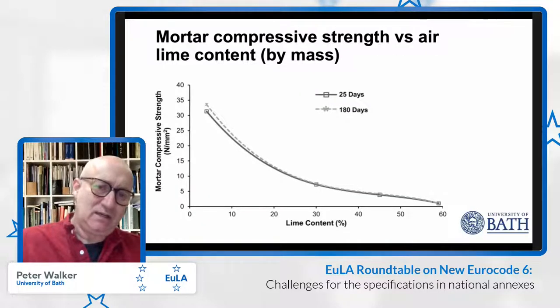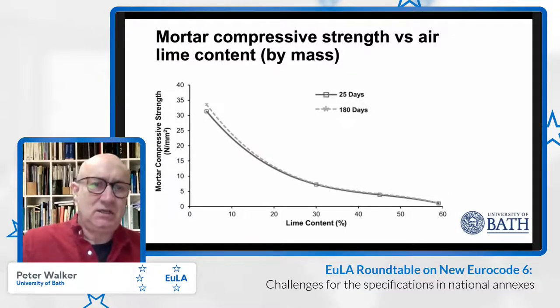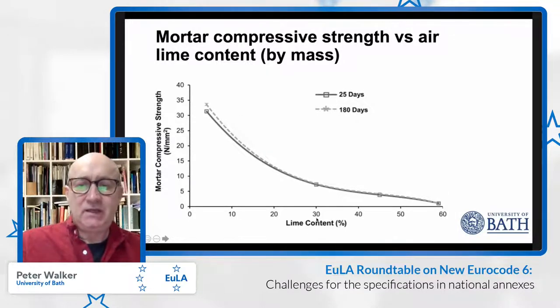Presented graphically, you can see the change in mortar compressive strength with percentage lime content. As said earlier, there was actually some lime in that CEM I mix from some calcium hydroxide from the cement, so this is why it is not presented precisely at zero there. Then we see a decrease in the mortar strength with the increasing lime content, exactly as we'd expect and as previous research has reported, and not a great deal of difference in performance between 25 days and 180 days.